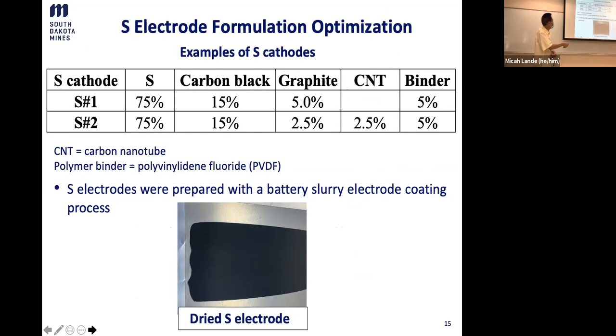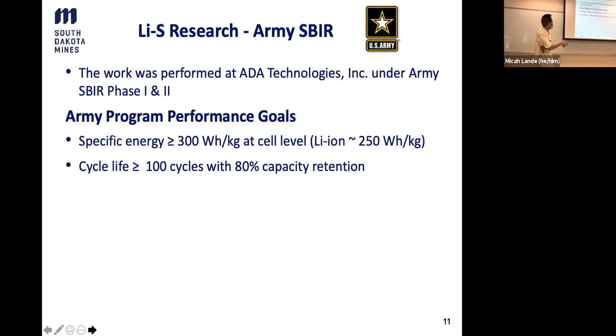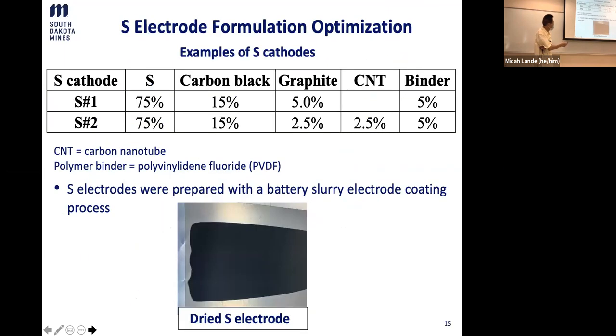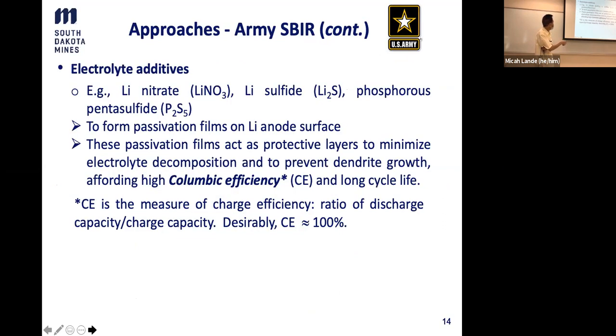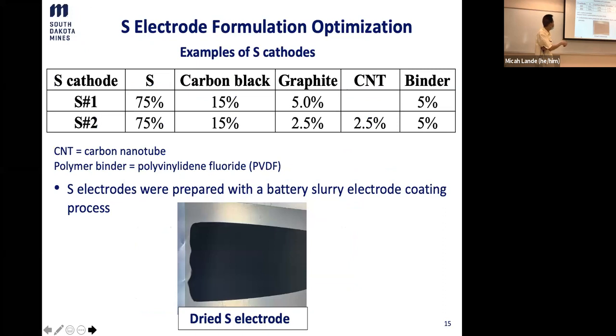carbon nanotube. And then the other component, as I said, is the sulfur as active material. So in theory, for the lithium-ion battery, that's the battery in the cell form, this amount is about 90%, more than 90%. Typically sometimes even 92%. The reason being, the cathode material is not very insulating. Itself is very conductive. So you don't need as much of the conductive medium to help increase the conductivity. And that's one of the challenges for sulfur.